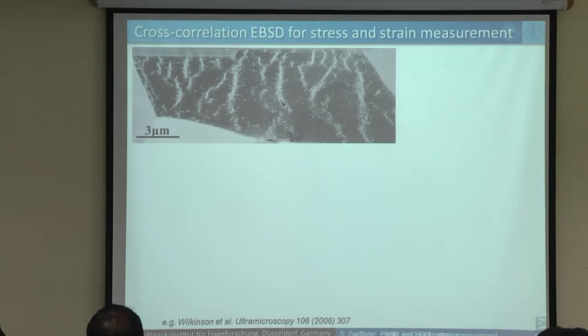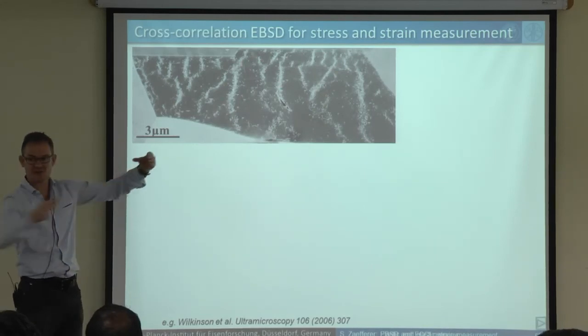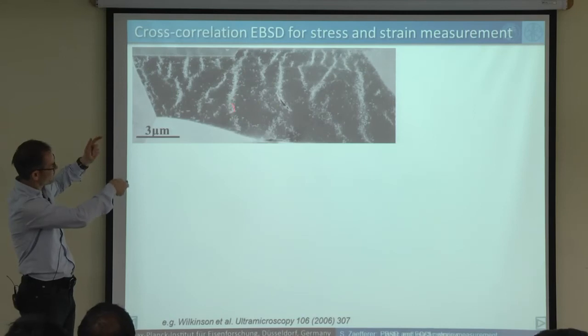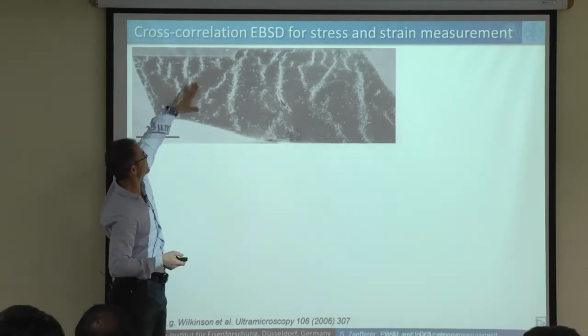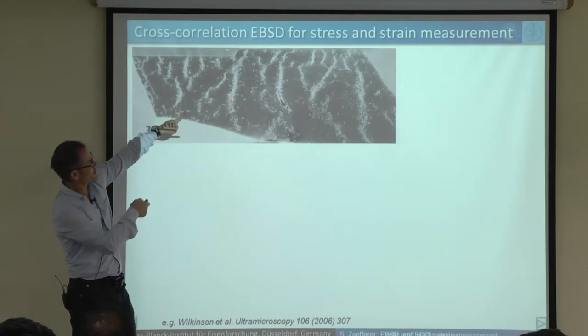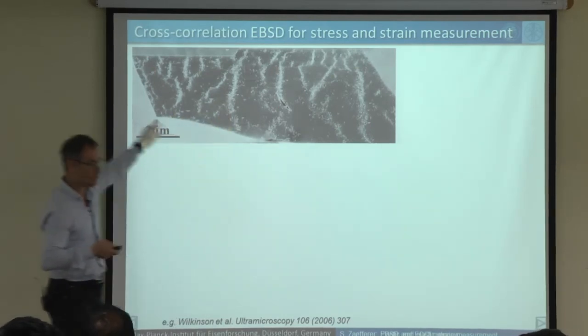Yeah, okay. When you do ECCI on a material which has been fatigued, so we actually did a fatigue experiment inside of the microscope. You have a little tensile compression test sample inside of the microscope, and you can move it and you can see how these dislocation structures form. In fatigue, it's well known that after 100 cycles already, the dislocations start arranging in very dense arrangements, with almost no dislocations in the channels and heavy dislocation densities in the walls.